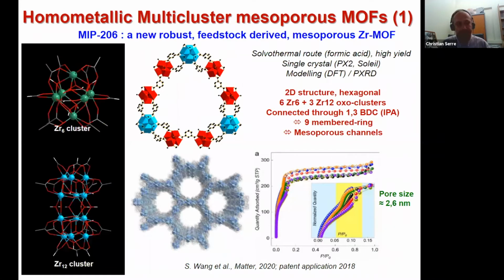So recently, we reported a new way of making mesoporous MOF. It is called the homometallic multicluster dots strategy, HMD. In this case, instead of having two different building units made from two different metals, we use the same metal, but with two different building units. Here, this is based on zirconium-6 and zirconium-12 clusters. We use solvothermal conditions with formic acid, and a very simple bio-derived isophthalic acid, 1,3-benzene dicarboxylic acid, and